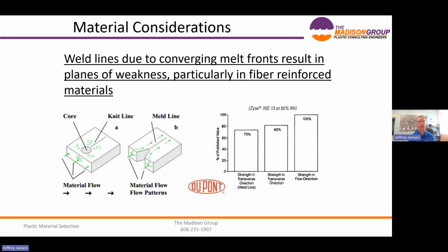Weld lines, again, another attribute related more to the molding process. Knit lines, weld lines are going to be formed during the molding process whenever we have two flow fronts that come together, particularly egregious in fiber reinforced materials, and our strength is going to be weakest at that knit line location. When those flow fronts come together, we may not get good entanglement of our plastic materials, and if you didn't know that, plastic materials fail mechanically through disentanglement. So if we don't have good entanglement, good fusion at those knit lines, we're going to have an inherently weak location. Again, how strong is your material?